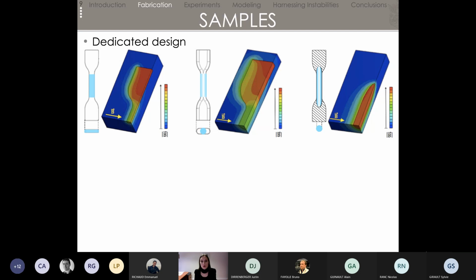So that's why we went for the second type of sample initially, which are also dog bone shaped samples, but this time the cross-section is circular. And now it's better because you can see that in the gauge area, we finally have uniform magnetization. However, you can see large gradients in the heads, so those red, orange, and so on. And we were wondering how this may contribute to the response of the sample.